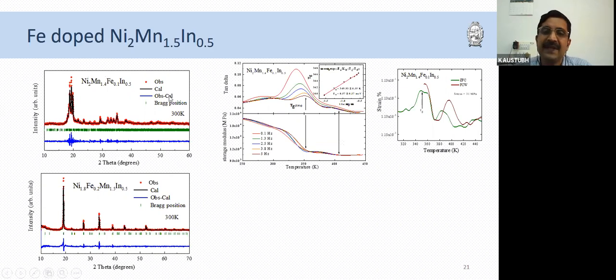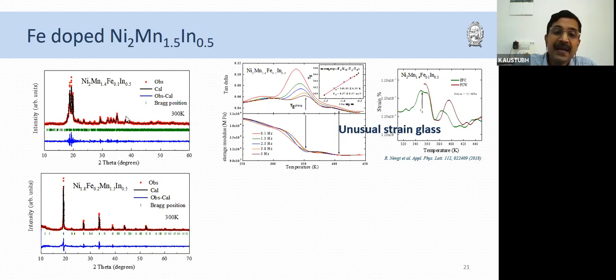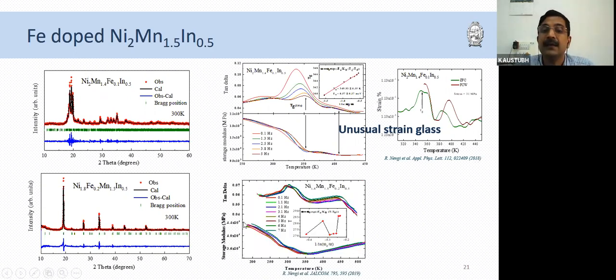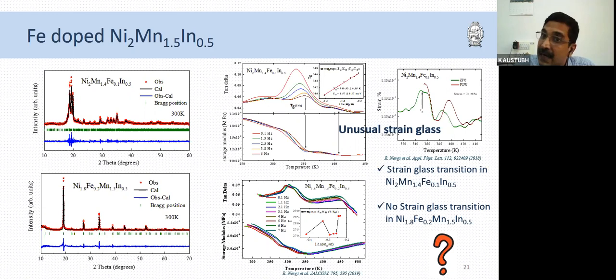In the case of MnFe, we see a frequency dependence of elastic properties and a Vogel-Fulcher dependence, and also bifurcation of field-cooled and zero-field-cooled strain. Therefore we called this an unusual strain glass because the structure was still martensitic. Whereas in the case of NiFe, we don't see frequency dependence, although the structure is cubic, which is what you expect for a strain glass, the invariance of structure across the transition, but there is no property. So the question is, you have a strain glass in MnFe, you don't have a strain glass in NiFe. So what is happening? How do we understand this?